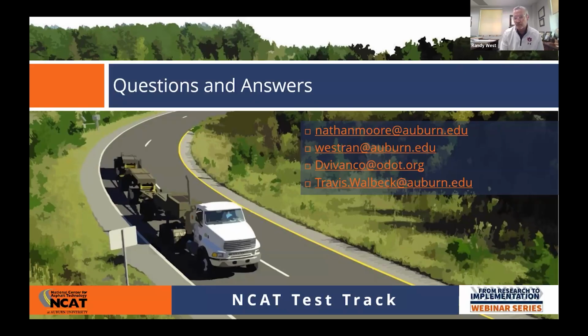We have an accelerated weathering system at NCAT. There are not very many of them around the country that do weather, UV light, temperature, and moisture. And we use that accelerated weathering system in some of our research, but it is a very time-consuming process in itself. I think it takes about a month of aging in that weathering system to simulate a couple of years in the field. And so that's just not useful for day-to-day mix design or QA practices. Randy or David, jump in.